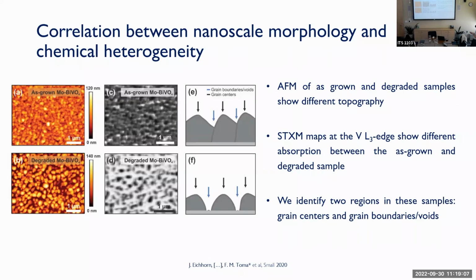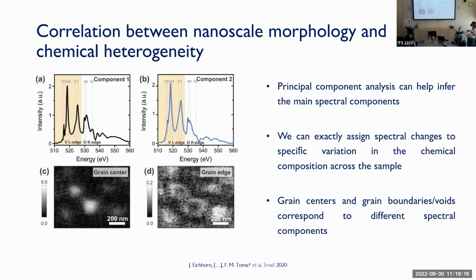and the grain centers. And we focus on these two areas to understand the differences in X-ray absorption spectrum. We found basically two components that were also confirmed by principal component analysis. And these two components are indeed related to the grain center and the grain edges.